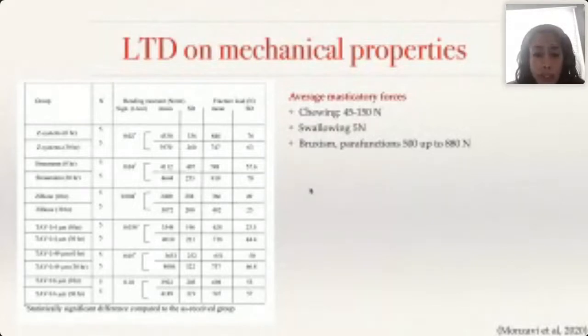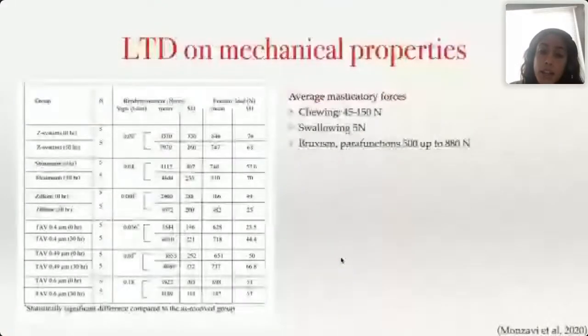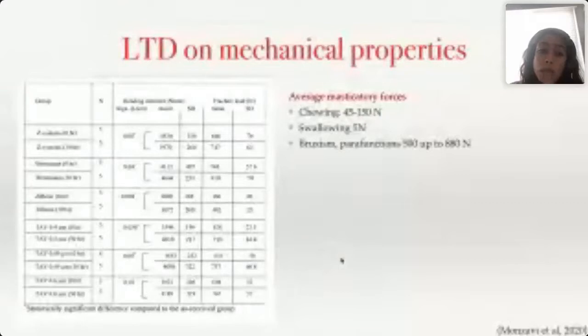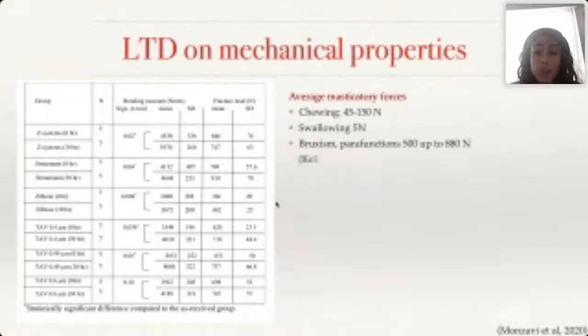What's important here is that manufacturing procedures are important. These are all different zirconia implants, but our results, though all pretty high, are different between implant systems. So when we have patients that are bruxers, I would be careful and look at these numbers, and make sure to have them use an occlusal night guard, or in some cases they may not be a good candidate if we're using implants with a lower fracture load. This is something important to remember.